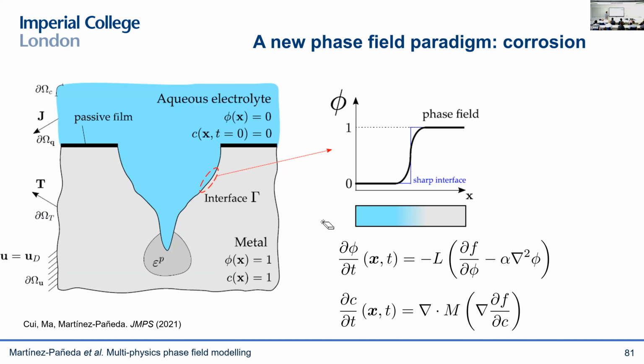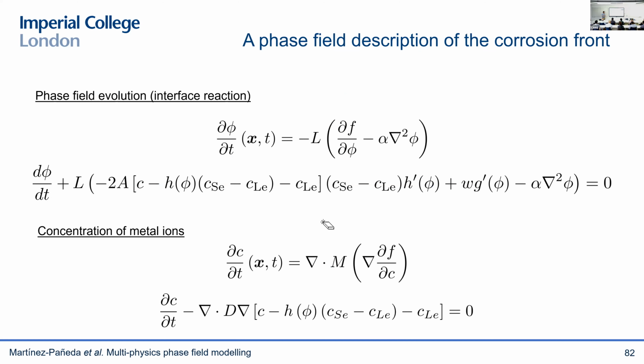But again, this seems like a good idea to use the phase field paradigm for. So it's a bit different than fracture mechanics, but it's kind of the same idea. So the phase field now describes the aqueous electrolyte-metal interface. And I won't get into the details of how we formulate these phase field models, but they're closer to these solidification models that people use in the condensed matter physics community rather than the fracture mechanics ones. But essentially, the easiest model that we have is based on the KKS model. It has two equations. One describes the interface reaction, so the phase field simulating atoms detaching, so the corrosion process itself.